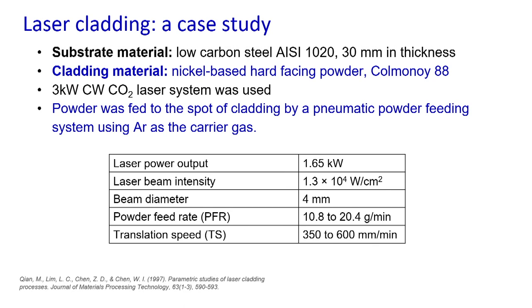Now let us have a case study on laser cladding. Here we are taking a low carbon steel, AISI 1020, with a thickness of 30 mm, and we are cladding a nickel based hard facing powder over it. To clad the nickel based hard facing powder, Colmonoy 88 material, we are using a 3 kilowatt continuous wave CO2 laser. The powder is fed to the spot of laser cladding by a pneumatic powder feeding system, and argon is used as the carrier gas, as well as the inert gas.